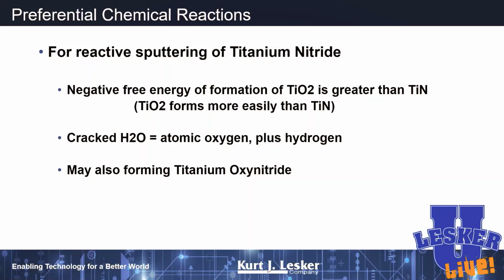So in this case, it really behooves you to try to pump to a very, very low pressure, to pump away as much of that oxygen, as much of that water as you can. It also behooves you maybe to keep your chamber closed up and under vacuum when you're not using it, just to try to keep it from getting really, really wet. I mean, you can put hundreds and hundreds of layers of water on the walls of a vacuum chamber without really trying.